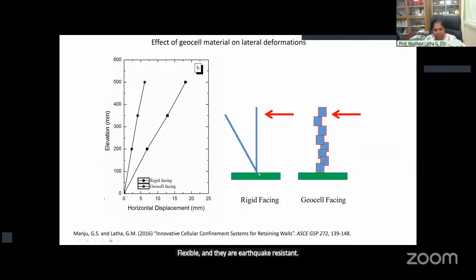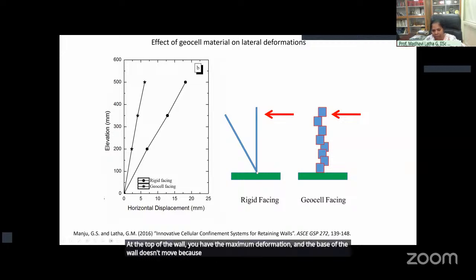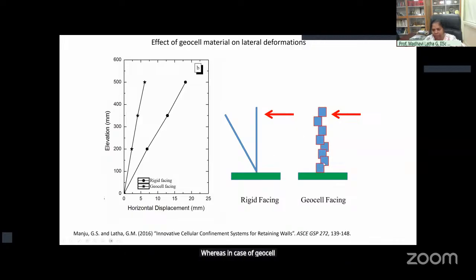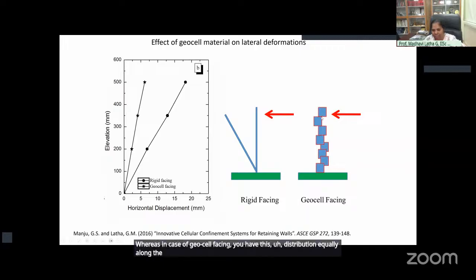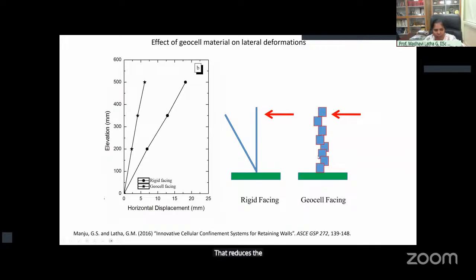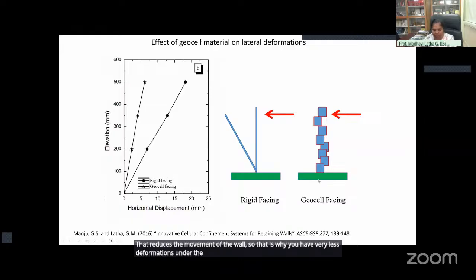In the case of a rigid wall, when we compare, this is the kind of deformation that you expect. At the top of the wall, you have the maximum deformation, and the base of the wall doesn't move because it is fixed. Whereas in the case of geocell facing, you have this distribution equally along the height of the wall, which reduces the movement of the wall. So that is why you have very little deformation under the influence of earthquake forces.